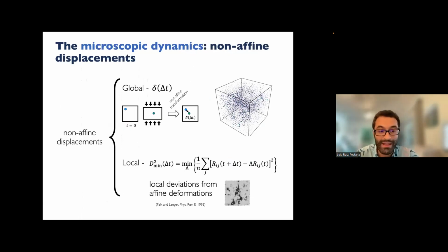So we quantify the microscopic dynamics in two ways. Well, it's one way, really. It's looking at the non-affine displacements. You have a box full of marbles that are deforming. The box is deforming, the marbles are moving. So the best way to characterize how much they move and when they move is non-affine displacements. So these are basically displacements where you subtract the bias of the overall deformation.